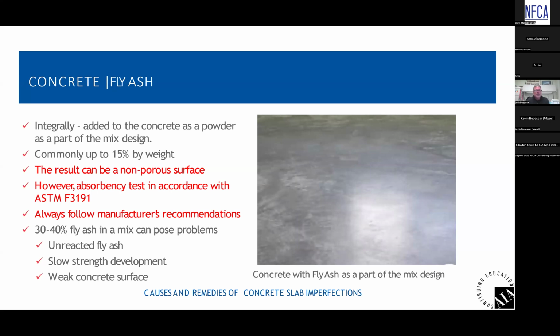But typically, a rate of about 15% by weight is pretty common, and manufacturers are good with that amount of fly ash in concrete and it's not causing problems for patching and leveling materials, or adhesives and floor covering, things like that. But the problem is that most people think the concrete is like normal concrete, very absorbent. But what can happen is when you add fly ash to concrete, it makes the concrete more dense and less absorbent. So the absorbency standard from ASTM is F3191.